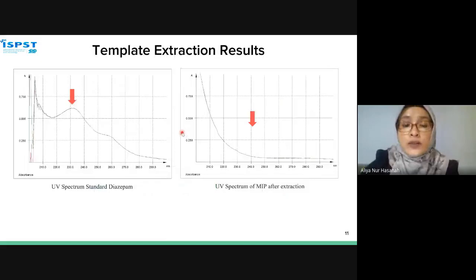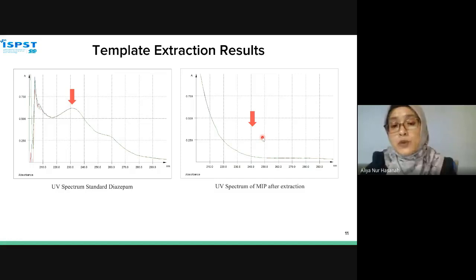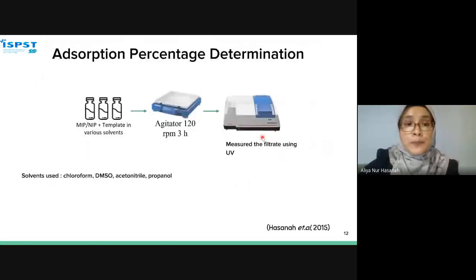This is the result of the monitoring of the diazepam template, and we found that in the UV spectrum of the MIP after 10 extractions, we couldn't find any maximum wavelength of diazepam anymore. So it means the extraction is already completed. After we know that the template is already extracted, we continue the process with adsorption percentage determination.